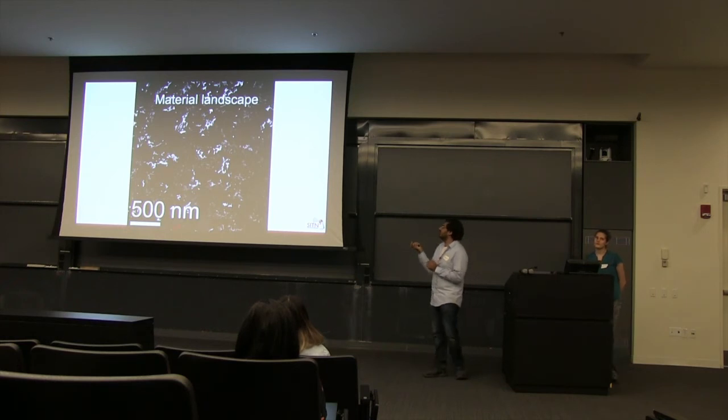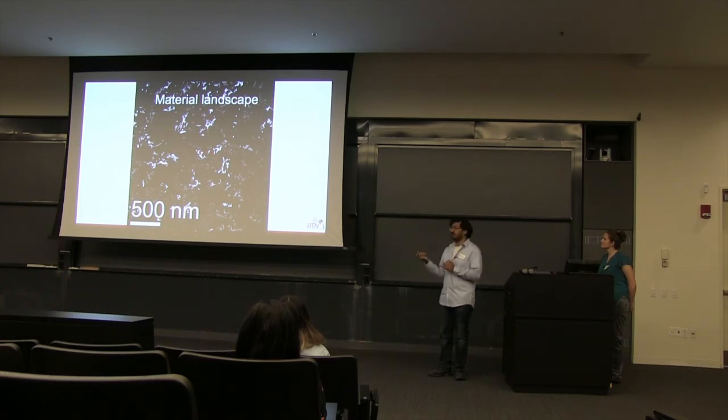And so when I do that, this is what the image looks like. So this gives me a lot more detail about my material. It immediately tells me what the size of these crystals is, how they're arranged, how frequent they are. So for example, one of the really useful pieces of information for my colleague was that each of these crystals is something like 50 to 100 nanometers big, so he can begin to understand more about his growth process.